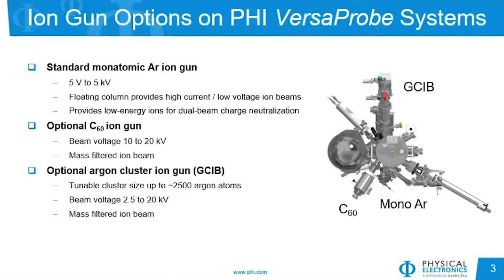That can have a beam voltage of up to 10 to 20 kV and is a mass filtered ion beam. We also have an argon cluster ion beam, or GCIB, where we can tune the cluster size from around 620 to around 2500 argon atoms, and that has a maximum voltage of 20 kV, and that is also a mass filtered ion beam. As you can see on the schematic on the right side of a VersaProbe system, we do have the ability to mount all three of these guns on the system at the same time. And so you can choose, based on your application, which gun is going to be most appropriate, and then select the ion gun that is best suited for your work.